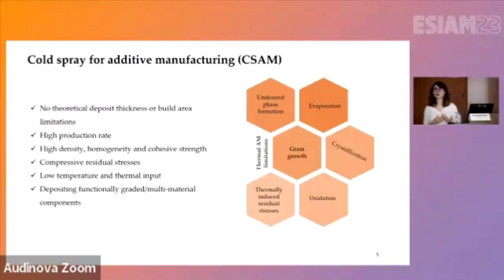We get compressive residual stresses because of the pinning effect and the plastic deformation, rather than the tensile residual stresses that we normally have in thermal-based additive manufacturing techniques. We have, of course, the low temperature. We are way far from the melting temperature of any material that is involved, so we would avoid all the problems regarding, let's say, the grain growth, undesired phase transformation, oxidation, crystallization, all the problems that are coming with the melting and solidification of the material. So that would give us a lot of flexibility.